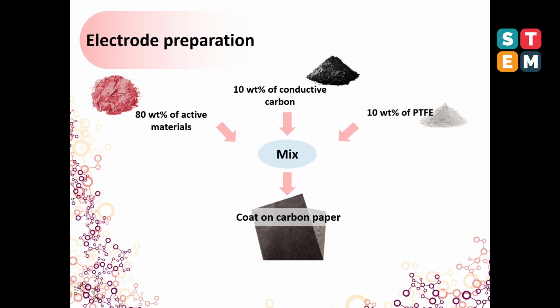The active material after treatment was prepared as a working electrode by mixing with PTFE and conductive carbon. The mixture was coated on a 1 cm² area of carbon paper that was used as the current collector.